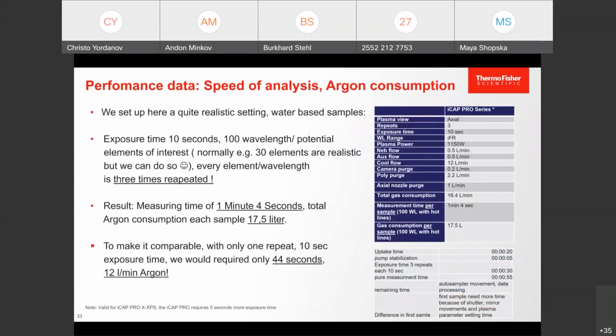So coming to another point: running cost, speed of analysis, and argon consumption. We did not try to generate the fastest measuring time or the lowest gas consumption. Our exercise was based on a real life exercise. This means exposure time 10 seconds. We checked 100 wavelengths because we can do it. Nobody is interested in 100 elements. Normally you run 30, 20 elements, I don't know. But the number of elements is not relevant for our unit. What we did is we repeated every measurement 3 times, every element repeated 3 times for quality reasons. We had a measuring time of only 1 minute and 4 seconds and a total argon consumption of 17.5 liters.